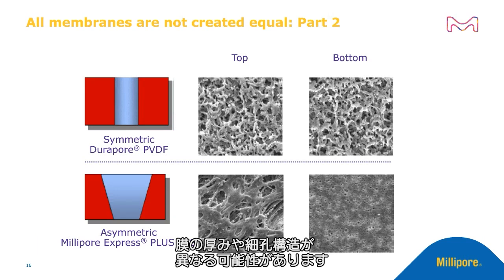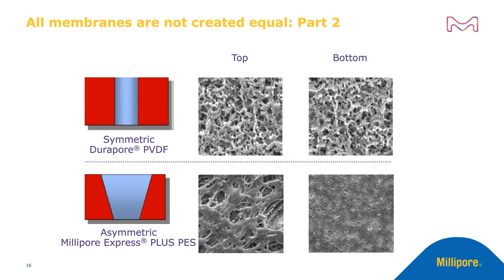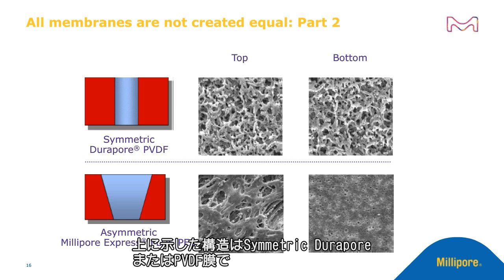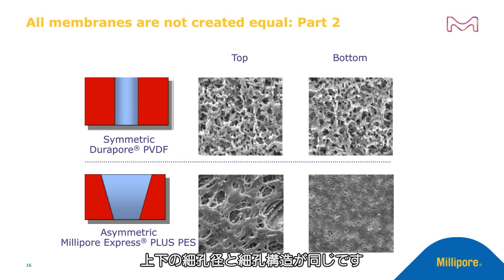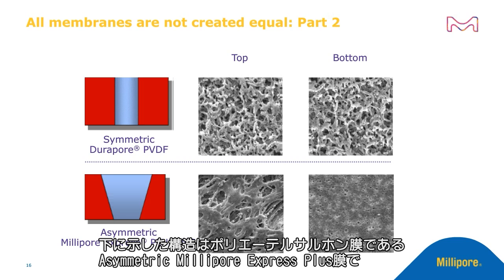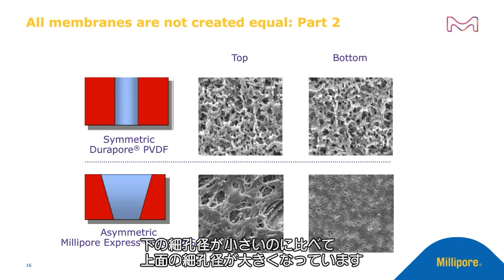Sometimes the membranes might have the same pore size, but their pore structure across the thickness of the membrane can vary. The structure shown at the top is a symmetric Durapore or a PVDF membrane, where the pore size and pore structure is the same at top and the bottom. Whereas the bottom panel shows an asymmetric Millipore Express PLUS membrane, which is a polyethersulfone membrane, where the top surface has larger pore size compared to the smaller pore size at the bottom.